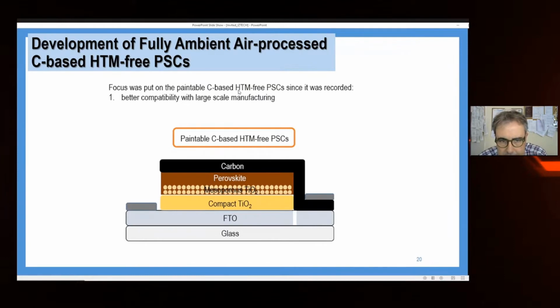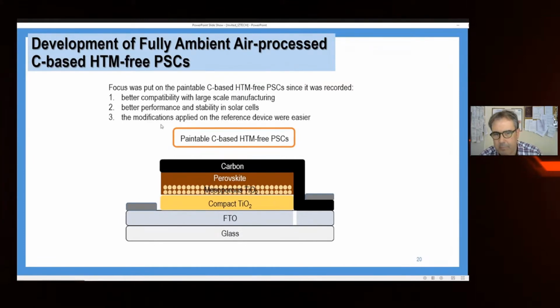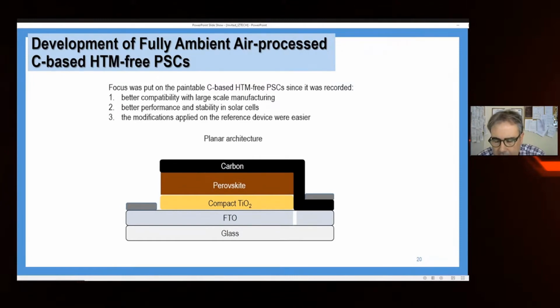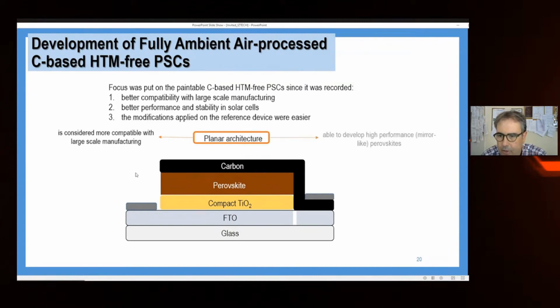As I said, and I say again here, with this structure we may achieve better compatibility with large-scale manufacturing. We have better performance and stability in the solar cells. And finally, we can make some modifications which are easier than in the case where we follow the typical structure made with these organic materials, HTM and gold. Of course, we can use an alternative structure which is simplest for the companies. It is the planar, where we have removed the mesoporous titanium dioxide, and we use only a very thin layer of compact titanium dioxide. This planar structure, as I said, is more compatible with large-scale manufacture. You can imagine why. And of course, it is able to develop high performance, mirror-like, I would say, because the crystal quality of perovskite is better.